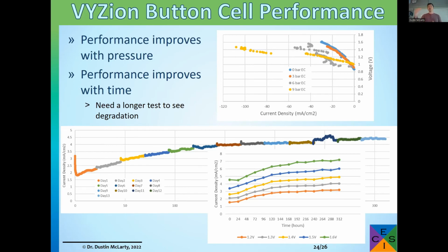So still an order of magnitude lower current than we'd like, but this was with a rather thick pellet. This printing method at the moment, we're still making very thick samples. This was about 800 microns thick for the oxygen conduction length. So we see the opportunity to make it 10 times thinner, which should very quickly get us to 10 times more current. So we see the potential there.